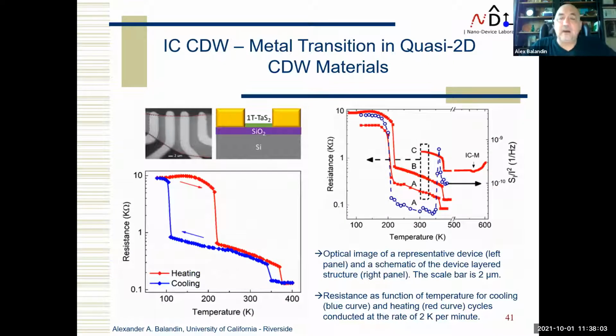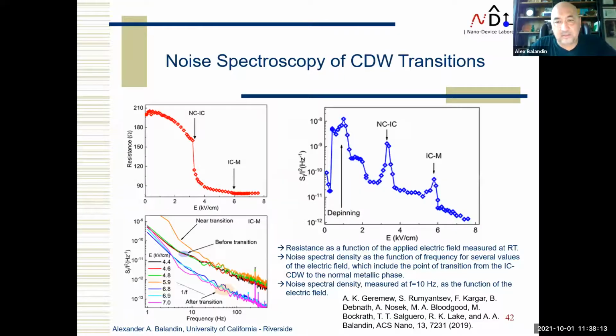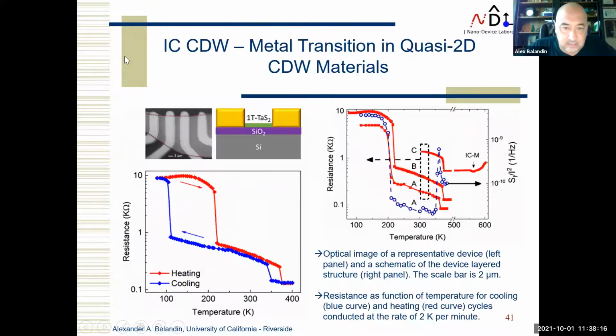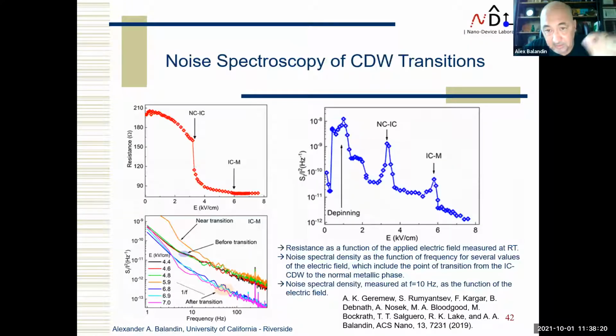Okay, now because I have to watch the time, I would like to say we then used noise spectroscopy further to observe all the transitions. One of the things is that the transition to the metal state has very little change in resistivity. If you look at the left picture, this is the transition from nearly commensurate to incommensurate, and this is the transition from incommensurate to metallic, with very small change in resistivity. However, noise is very sensitive.